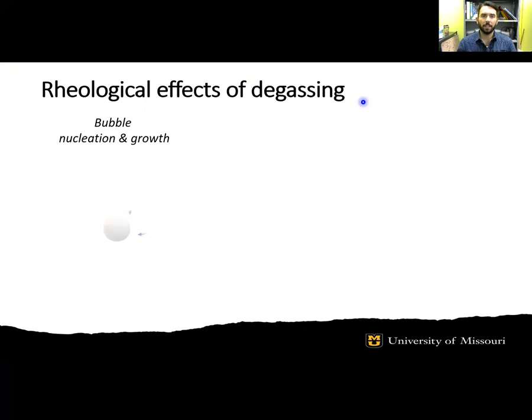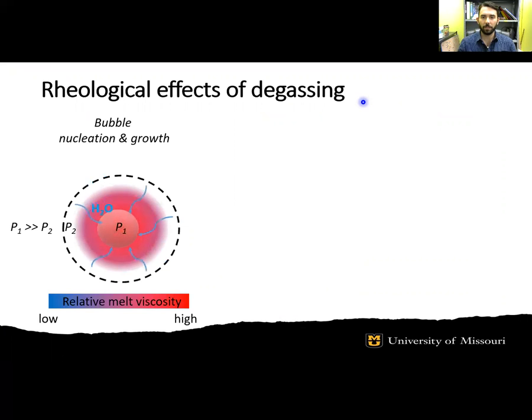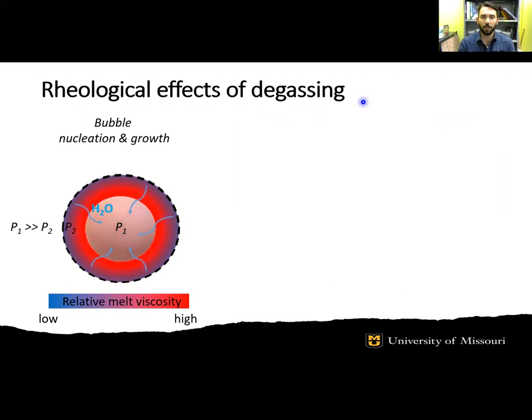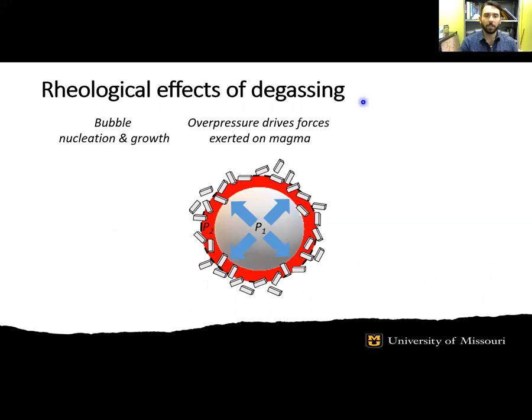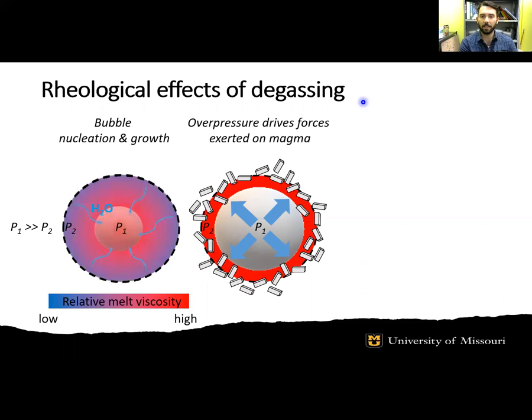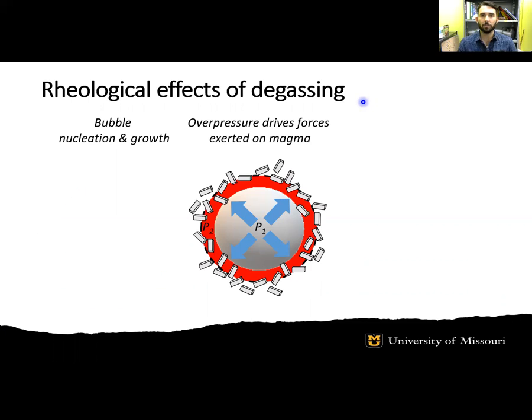During inflation, degassing would increase local melt viscosity by creating a dehydrated halo, which further drives diffusion of volatiles, slowing viscous deformation. The overpressure provides the force exerted by an expanding bubble on the surrounding magma. And as we know, depending on the magma's crystal content and strain rate in response to this internal stress, brittle failure can and does occur in our samples at high crystal fractions greater than 0.6.